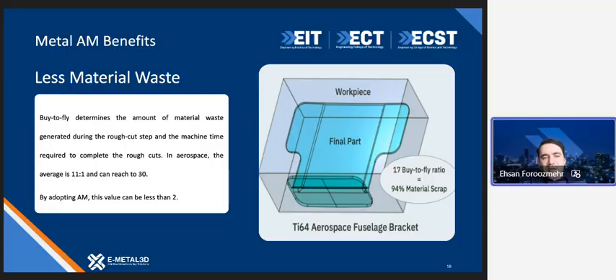So it is very common in aerospace specifically, where the part has to be thin enough and light enough, that the ratio reaches 11 to 1 or even 30 to 1, meaning you're wasting 30 times more material than you are using. But when we talk about additive manufacturing, that number can go down to 2 or even less. It means if you have a 1 kilogram part at the end, you're using at most 2 kilograms of raw material. So that's a huge difference between the two technologies.